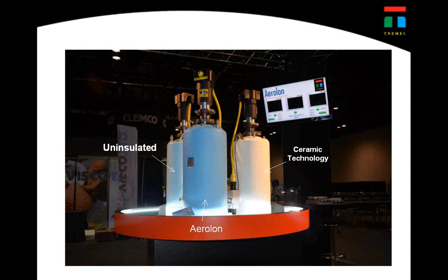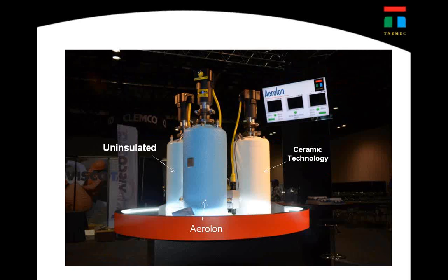So we basically have these 3 tanks, and they all have the same thickness, all on at 150 mils. And you can see in this next slide, the Aerolon coating, we're showing energy efficiency. What we're trying to do is keep these tanks at a constant temperature. How much energy does it take to maintain the temperature of a liquid? The liquid inside these tanks is water, being maintained at 160 degrees F. So they looked at the efficiency of the thermal coating on the outside to see which one would keep it constant and for how much cost. All the people in the oil and gas business were very interested in this because when you looked at the Aerolon technology, which you can see is at 47.6%, the control in the middle, which is uninsulated, and then a ceramic material at 22.8%, we were virtually 50% more efficient at the same thickness.